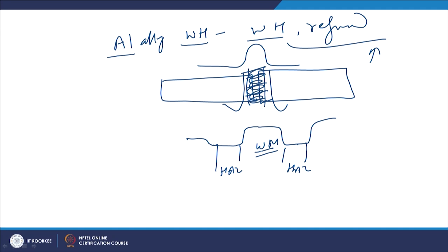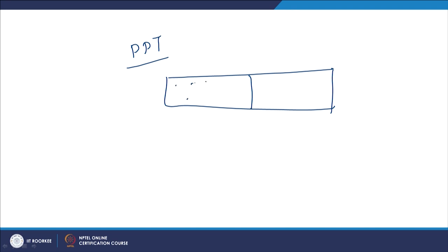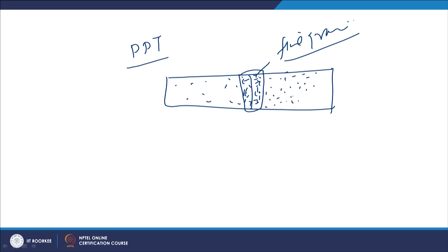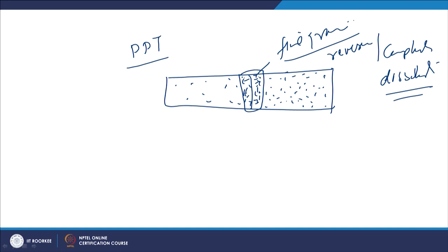On the other hand, what has been observed? So this is the case of the work hardening effect, where both fine grain structure as well as work hardening effect will be imparted. On the other hand, if it is a precipitation hardenable aluminum alloy which gets its strength from the formation of fine precipitates, then controlled plastic deformation of the weld metal near the faying surfaces will lead to a very fine grain structure, but the fracturing and controlled plastic deformation followed by high heat generation leads to the reversion and complete dissolution of the precipitates. So here this region has no precipitates but a very fine grain structure.